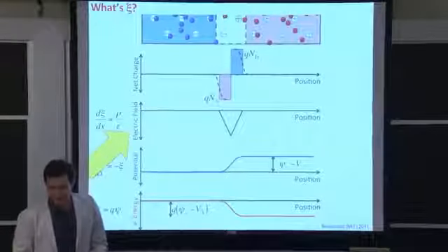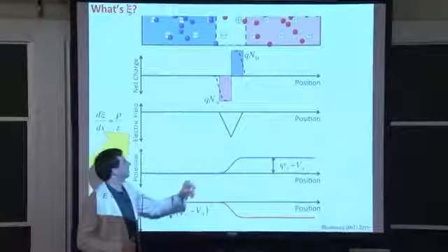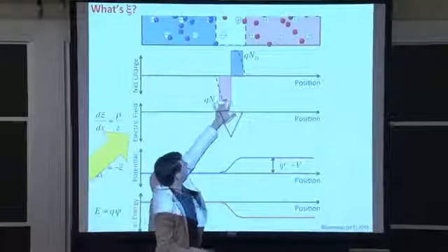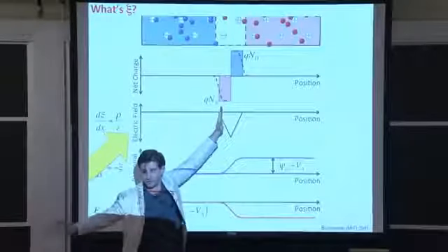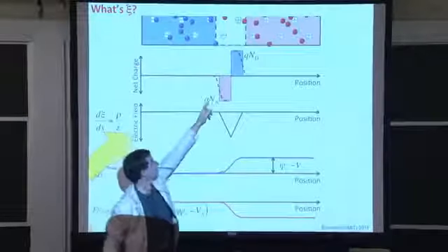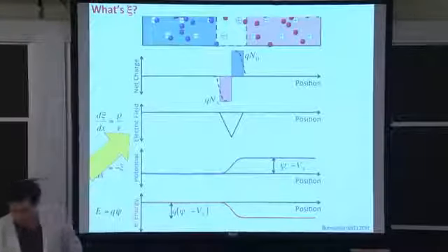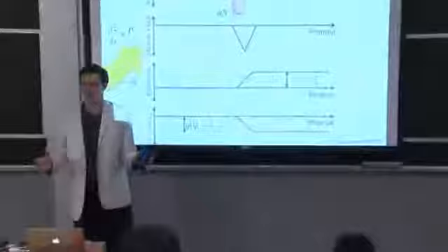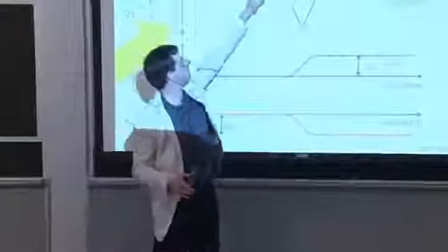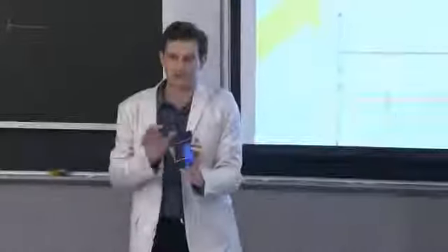Usually it's drawn flat, but is it just such a small effect? It's drawn flat anyway. So under applied bias, what happens to these charge distributions? Well, if you reverse bias it, you're essentially increasing the amount of charge on either side of the junction. If you forward bias, you're reducing it. So under forward bias, you probably wouldn't see the effect you're describing. Under reverse bias, the width of the space charge region, let's say, increases from 1 micron to 3 microns, and the thickness of the entire device is 200 microns. So I think it would still be a relatively small effect several tens of microns away from the junction. It really depends on the geometry of your device relative to the length scale of your space charge region.